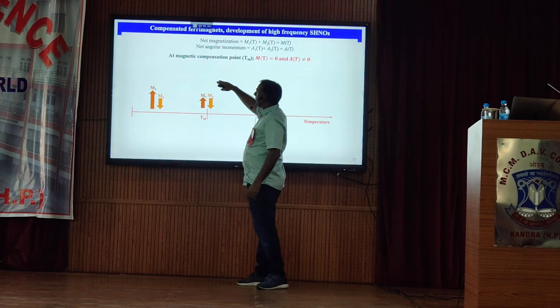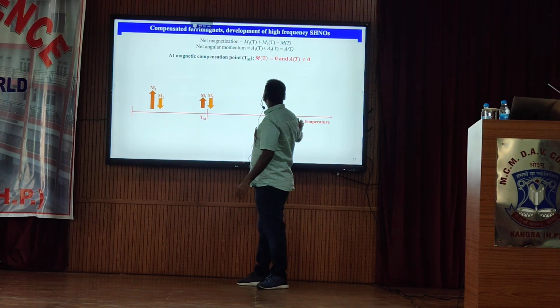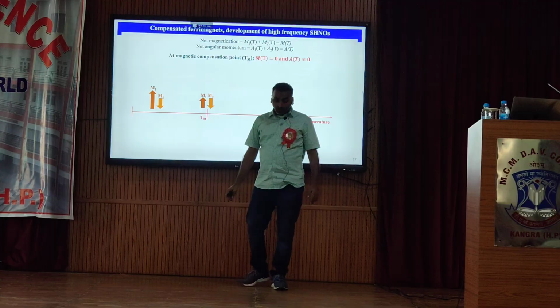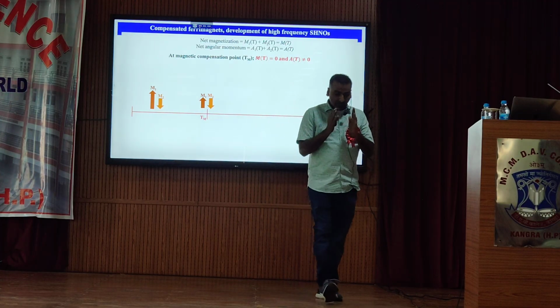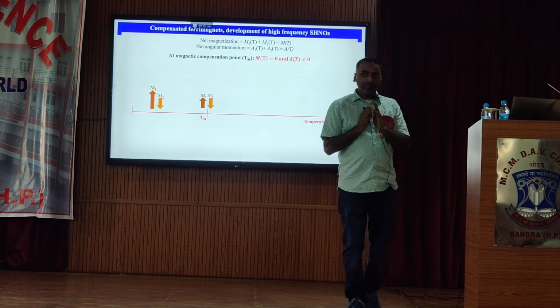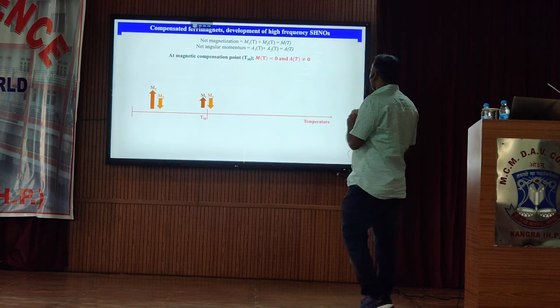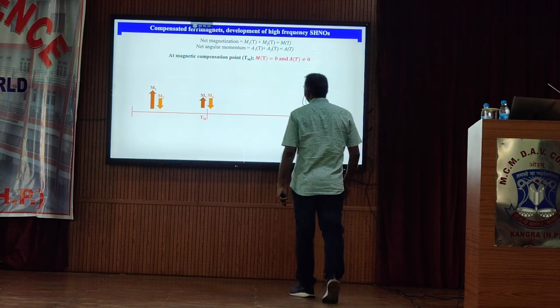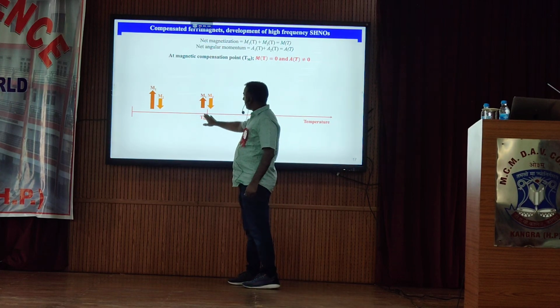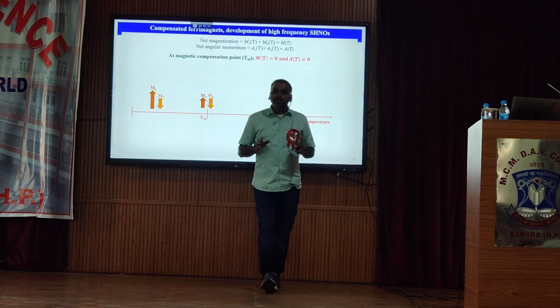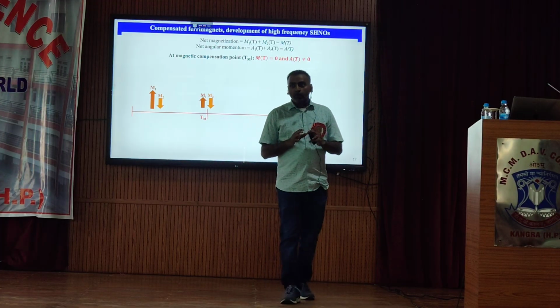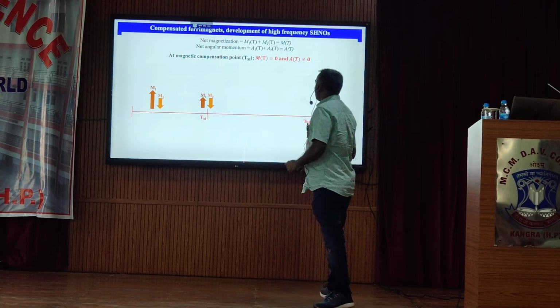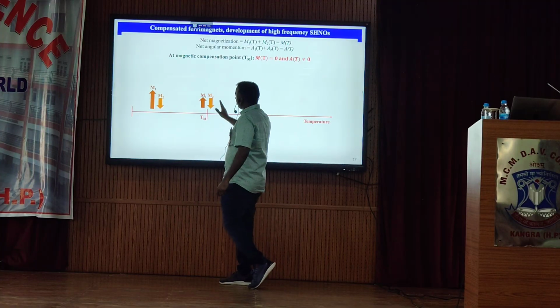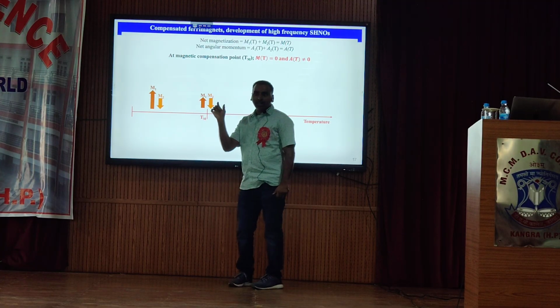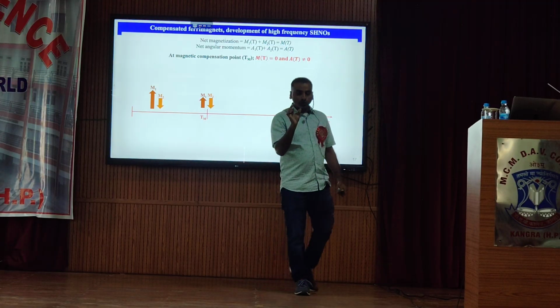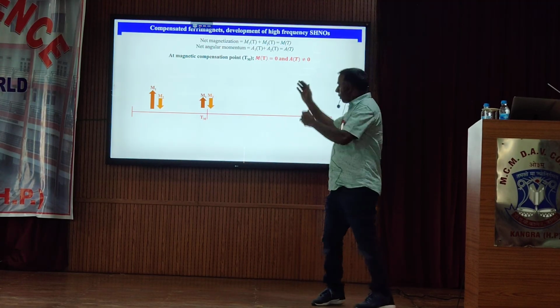They have a very interesting property in sublattice magnetization. At some temperature, there will be a situation where the two magnetic sublattices are equal and we get a net magnetization equal to 0. We are interested in the temperature range where we can work around this magnetic compensation point. The net magnetization is almost 0, but it's not 0. We work either on the left-hand side or the right-hand side of this point, so that we have some net magnetization, but the dynamics are close to ultrafast because of almost cancellation.